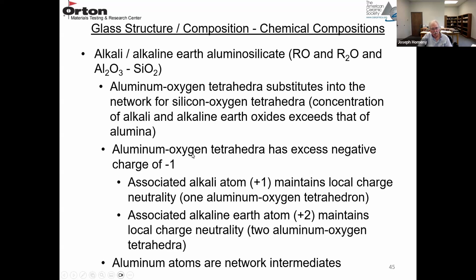So the aluminum oxygen tetrahedra has an excess negative charge of -1. So an associated alkali atom, which is +1, maintains local charge neutrality. So there's one aluminum oxygen, a tetrahedron. You can also have an associated alkali earth atom, +2, maintaining charge neutrality. So that would require two aluminum oxygen tetrahedra. So this is the case where there's excess alkali or alkaline earth, and the aluminum atoms are now network intermediates. They're forming these aluminum oxygen tetrahedra.